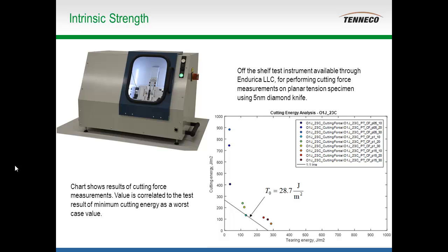So in this particular case, we get a measure of approximately 29 joules per meter squared. And so this effectively represents the threshold energy that if the energy within the stress strain cycle does not produce that energy level, a crack will not grow.